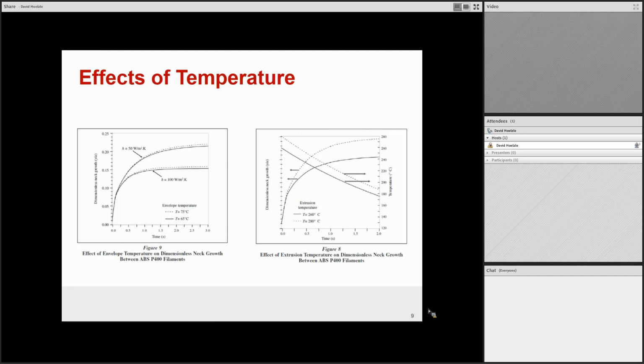On the left is the effect of the envelope temperature, so the ambient temperature of the 3D printer. And on the right-hand side is the extrusion temperature. What they noted is that the difference between the dotted line and the dark straight lines are relatively consistent changes in temperature. So the ratio of 260 degrees to 280 degrees is equivalent in terms of normalized ranges which you typically use for these processes. So they raise it a certain relative amount, and they determine the effect on the dimensionless neck growth.